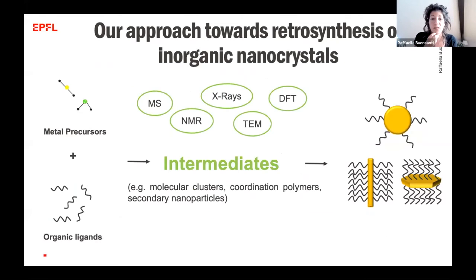So our approach to make some progress towards retrosynthesis is to look for intermediates. What forms between the metal precursor and organic ligands and the final nanoparticles? And what we and others are finding is that these intermediates can have really different chemical natures. They can be molecular clusters, or coordination polymers, or even secondary nanoparticles forming in situ. To characterize these intermediates, we really need a miscellany of different techniques, which span from mass spectrometry and NMR to X-ray and electron microscopy, and often we also need DFT calculations.